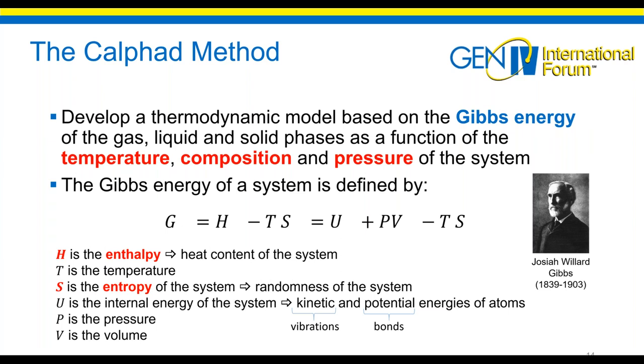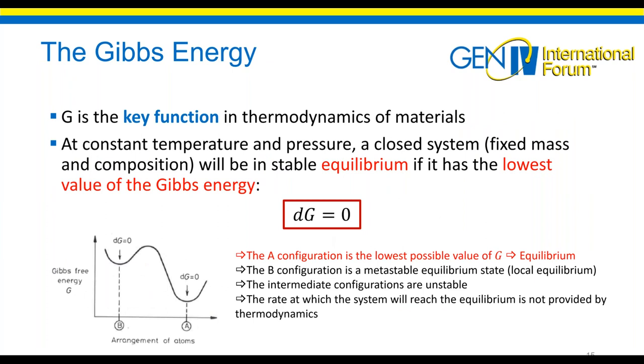system. So the Gibbs energy can be defined by the enthalpy H here, which represents the heat content of a system, minus the temperature multiplied by the entropy of the system, which has for physical meaning the randomness of the system. And in thermodynamics, you have a lot of relations. And thanks to this, you can also express it with the internal energy of the system, which is basically the kinetic and potential energies of your atoms. So this G function is really the key function in the thermodynamics of materials, because you can describe the evolution of your system with this and derive the equilibrium state of your system.